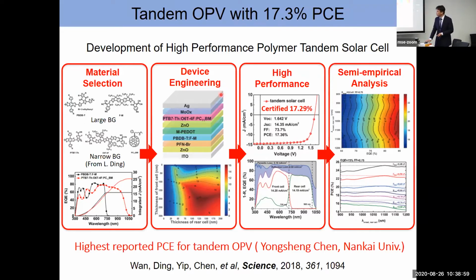And we also couple with this optical modeling, so we know the best architecture so that we can maximize the performance to 17%. And of course, we can do a further semi-empirical analysis. If we can further reduce the energy loss for both the large bandgap and the low bandgap OPV, we can even have a performance over 22%. And I can give you an update: it's already close to 20% for this tandem solar cell.